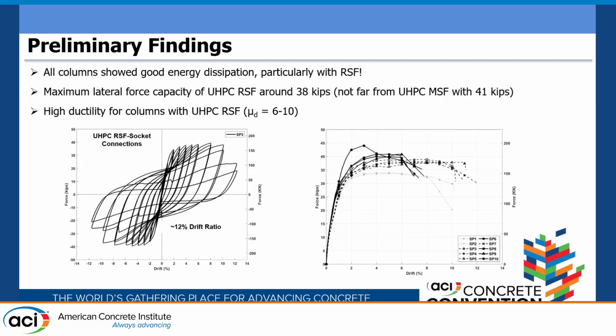So again, this testing was just a month ago, so we only have preliminary findings. But what we saw is that the recycled fiber has good energy dissipation. This is just one example of the hysteresis loops that we got. And also the overall backbone curves from all the testing, you can see the trend. The broken lines are from the recycled fiber, the solid lines are from the manufactured fiber, and the two are from the normal concrete.